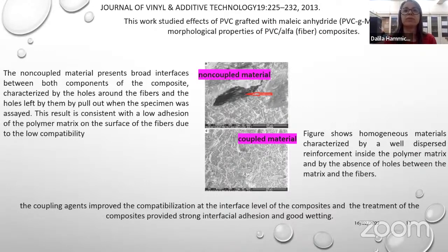According to this study, it must be noted that the coupling agent improved the compatibilization at the interface level of the composite. Confirmation of this effect was obtained from this SEM figure, where we don't use the PVC-GMA. We can see that it presents a broad interface between both components of the composite, characterized by the holes around the fibers and the holes left by them, by pull out when the specimen was assayed. This result is consistent with the low adhesion of the polymer matrix on the surface of the fibers due to the low compatibility.